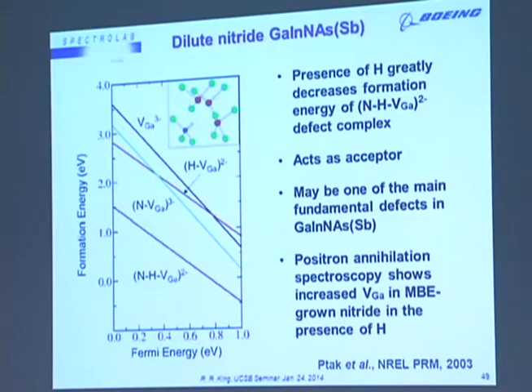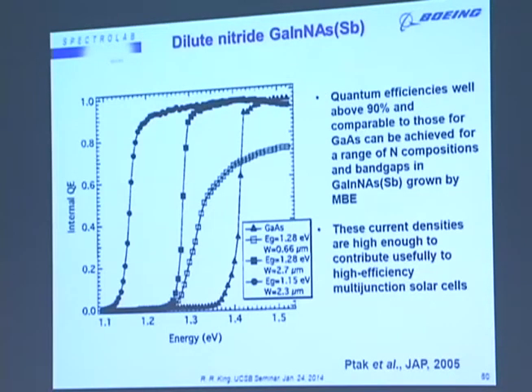It acts as an acceptor, and it's thought that this may be one of the main fundamental defects in gallium nitride arsenide. Positron annihilation spectroscopy also shows that when you have hydrogen present during MBE growth of this material, you also have an increased concentration of gallium vacancies. So the positron annihilation allows us to measure those gallium vacancies directly.